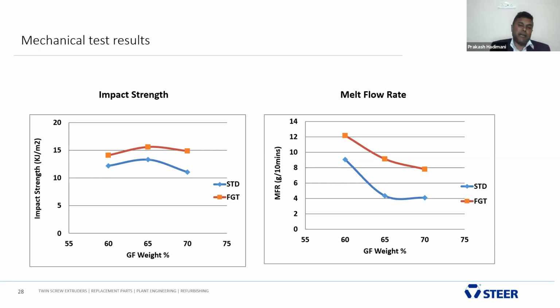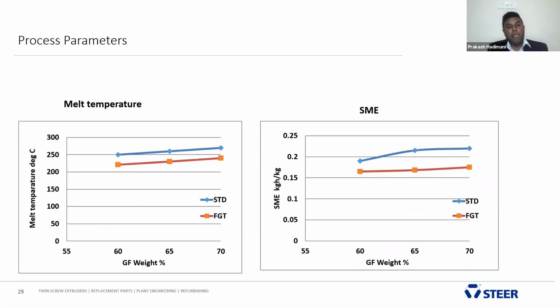When we are going for process parameters, next person. Okay. This is very interesting because Prasanna has already explained what is peak shear. Peak shear, when in the bilobe technology, during the melt, 2 to 3% of the melt is trapped completely when the two lobes contact together. That melt experiences enormous, high shear that leads to an increase in your melt temperature, that leads to the degradation of the polymer. That is what is happening here.